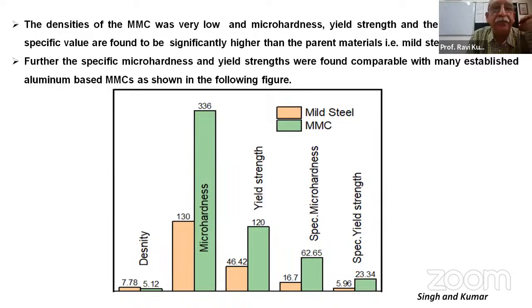And if you look at the density of the MMC and the strength corresponding to that, the mild steel density is 7.78 and this MMC density is 5.12. If you compare the micro hardness, it is almost 3 times higher than mild steel, and its yield strength is also 3 times the yield strength of mild steel. The specific micro hardness is also enhanced in a greater way, and the specific yield strength is almost 4 times that of mild steel.